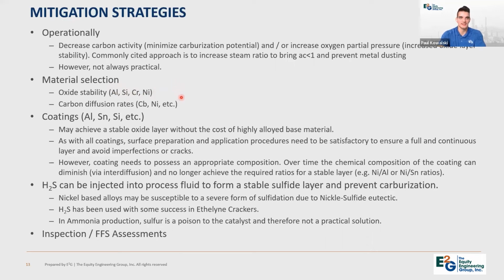And then a secondary item as well with material selection, there are some elements that actually reduce the carbon diffusion rate into the material. So if we can reduce the carbon diffusion, graphite isn't forming as fast, and then metal dusting won't occur as quickly. This isn't supposed to be a one-size-fits-all approach. Just wanted to highlight some of the items that should be considered when considering a material upgrade for metal dusting resistance.